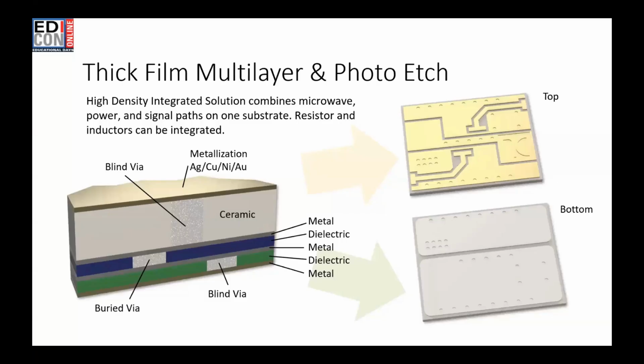So thick film, this is another example where we start with a substrate, we metallize the surfaces, and then realize the circuit. So the metallization could be using thick film, which is screen printing, and then it goes through the kiln or furnace, and when the surfaces are cured, then we can put dielectric layer and then repeat the metallization process again, and similarly keep doing this process to as many layers as required. Typically 6 layers are very popular.